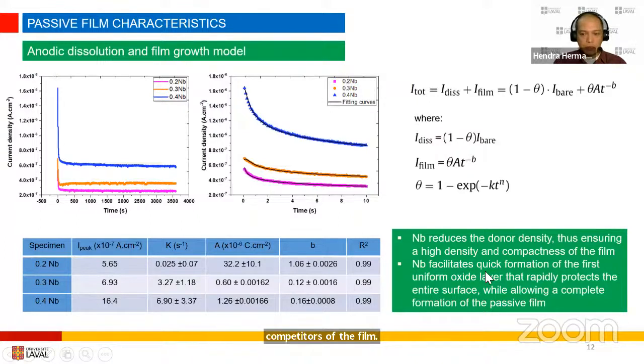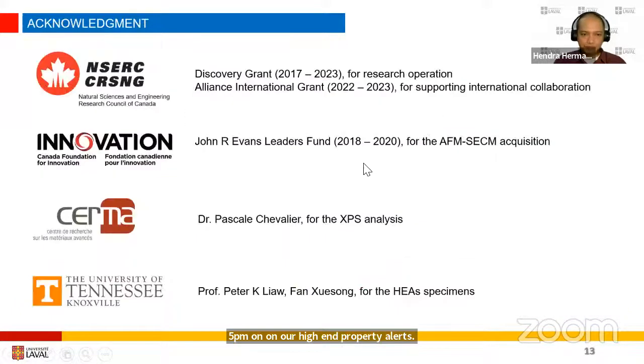Niobium facilitates quick formation of the first uniform oxide layer that rapidly protects the entire surface while allowing a complete formation of the passive film. So these are the beneficial effects of niobium. It improves the passivity of the passive film on our high entropy alloys. So that will be the end for now.